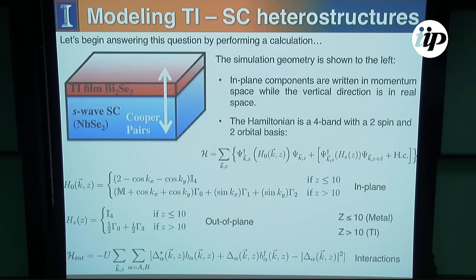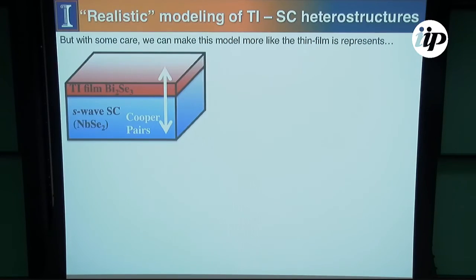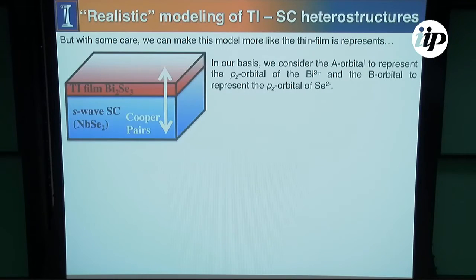Then, of course, we add the mean field density-density interactions, and I'll speak a little bit more about the size of the U that we chose. The A orbitals represent the pz orbitals of the bismuth atoms, and the B orbitals represent the pz orbitals of the selenium atoms.